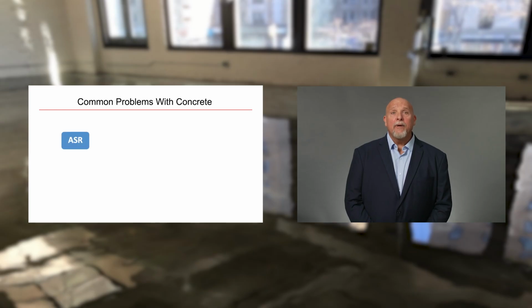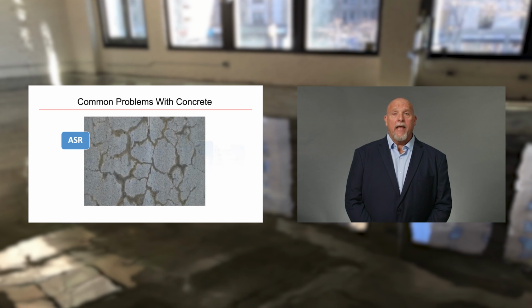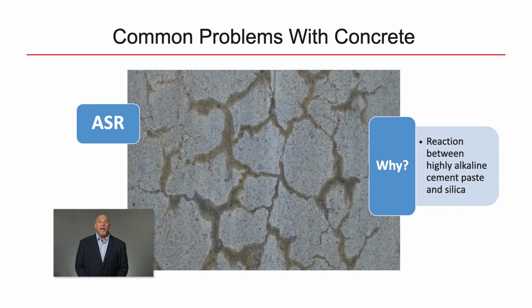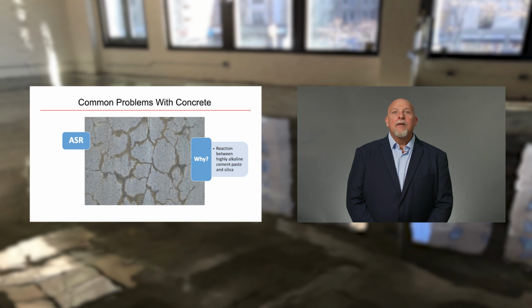Alkali silica reaction, commonly known as concrete cancer, is a harmful swelling reaction that occurs over time in concrete between the highly alkaline cement paste and the reactive amorphous silica found in many common aggregates, given sufficient moisture. This deleterious chemical reaction causes the expansion of the altered aggregate by the formation of a soluble and viscous gel of sodium silicate. This hygroscopic gel swells and increases in volume when absorbing water.